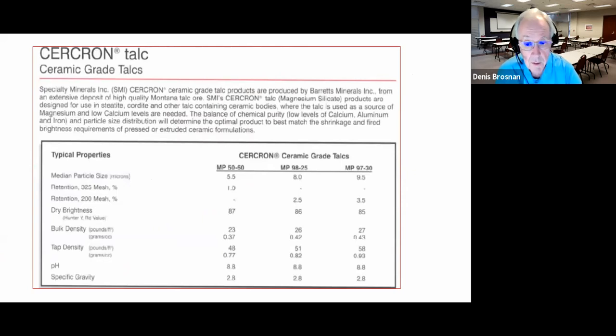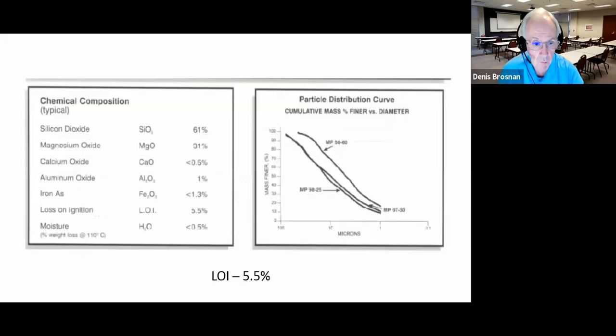Now, very quickly, here's a data sheet for a talc. I don't believe this talc is currently commercially available, but you can see that it contains magnesium oxide, about 31%. It contains silicon dioxide as the other major constituent. So it's a magnesium silicate mineral. Talc occurs naturally in the world in various deposits. It's ground and sized to reach certain particle size distributions as shown over here. One very important thing to mention is that talc has a loss on ignition of around 5.5%.